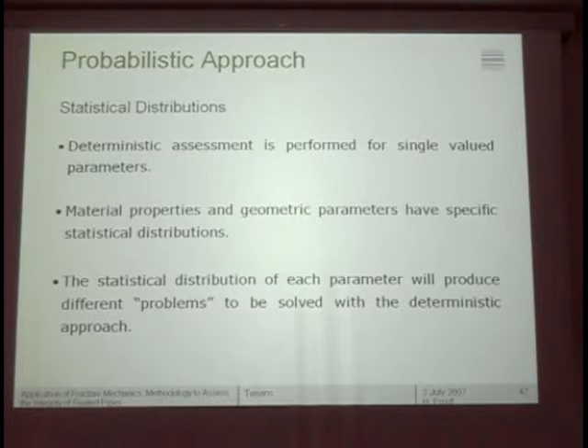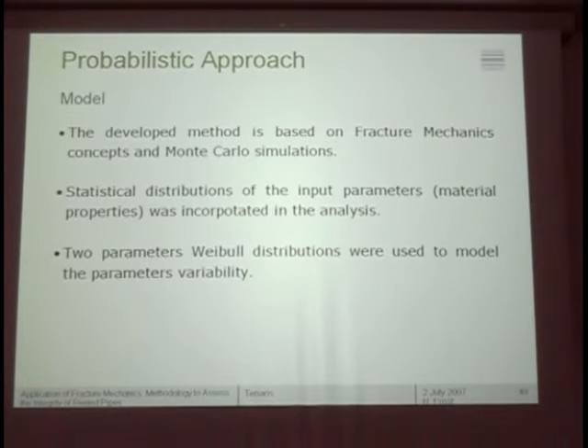Not solved, but giving some idea of the influence. So what we did is to develop a method based on fracture mechanics and Monte Carlo simulations, using as input the statistical distribution of these parameters, typically using a 2-parameter Weibull distribution for each of these.